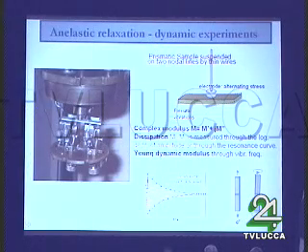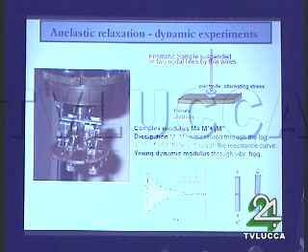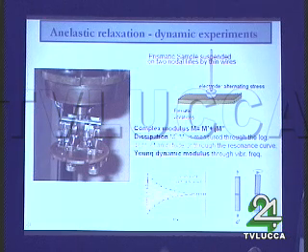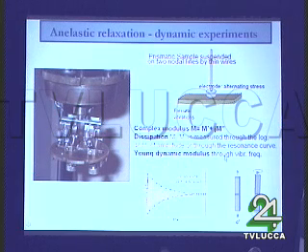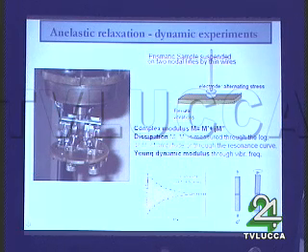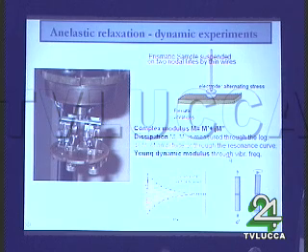This is a picture of the experimental setup. This is a rectangular sample, and the complex modulus, so the elastic susceptibility we measure, is given by the dissipation, which is measured through the logarithmic decrement of the amplitude or through the resonance curve, and the Young dynamic modulus, which is measured through the vibration frequency. So the modulus is proportional to the square of the vibration frequency.